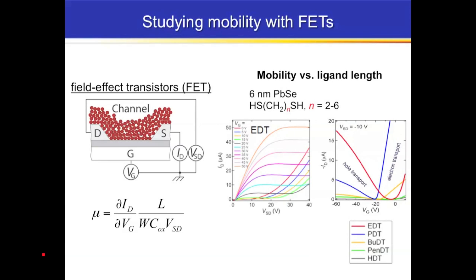And so we've been able to look at a number of basic geometric parameters of quantum dot films and study the mobility. One thing that we've done is we've looked at mobility versus ligand length, or the interdot separation. We did this using ligands which are alkane dithiols, and we just changed the number of carbons in the alkane chain from 2 carbons, which is ethane dithiol, out to 6 carbons, or hexane dithiol. And we can see here we've got this slope relationship.